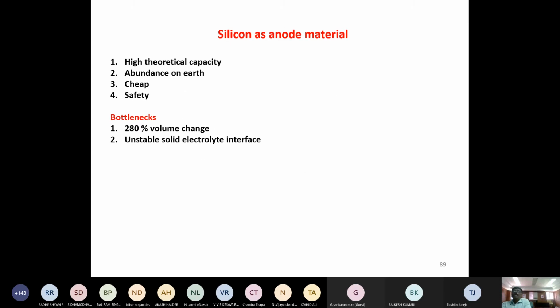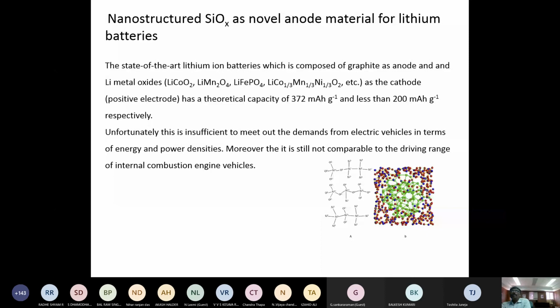So, and the last one is silicon. It's the last choice. But we can use silicon as anode because it has higher theoretical capacity than lithium metal anode, and the abundance is very huge on Earth and it's very cheap and safe. However, it goes through 280% volume change when you use it as anode, and this is high. It also forms an unstable solid electrolyte interface. So then finally, people have started working on SiOx, which is a non-stoichiometric material, silicon monoxide, and the derivatives. So it has a theoretical capacity of 1850 milliampere hour per gram.